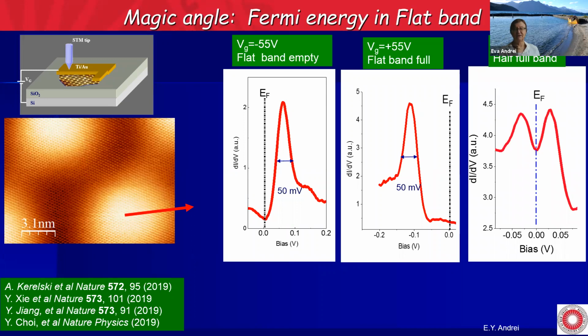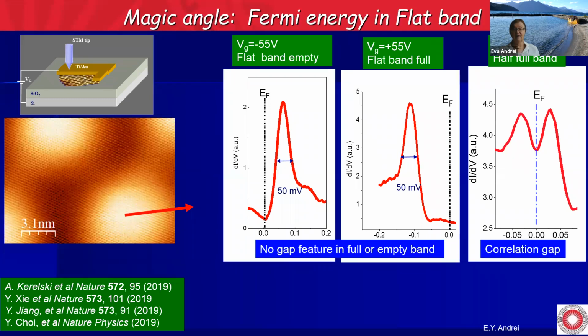And then we bring the Fermi energy within the flat band. Here it's right at charge neutrality, and we see this beautiful pseudo gap opening, which tells us that we have a correlation gap here. Now, the pseudo gap physics was shown in 4 papers that appeared pretty much simultaneously, and everybody saw this opening of a pseudo gap when you bring the Fermi energy within this flat band. The other details are different in these experiments, but I'm not going to go into them here.